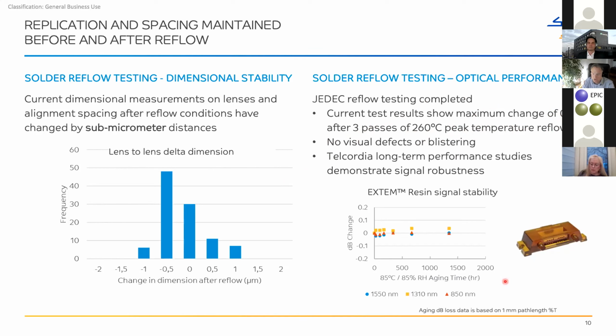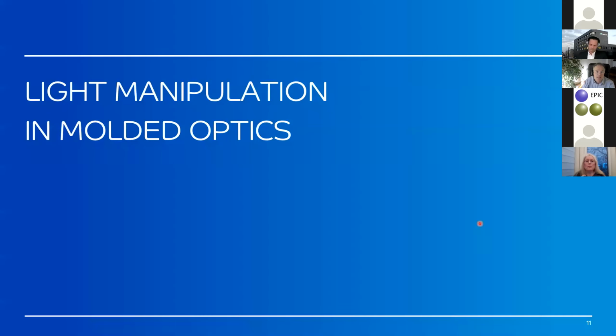We also, of course, have to look at long-term aging performance. There's an industry protocol like Telcordia that dictates that your part needs to remain stable for at least 1,000 hours if you age it at 85C and 85% relative humidity. We have done some tests with optical plaques where we actually translated the transmission to dB. And EXTEM does not get opaque or form blisters or whatsoever. So the dB loss is very minor. So that looks all pretty exciting.